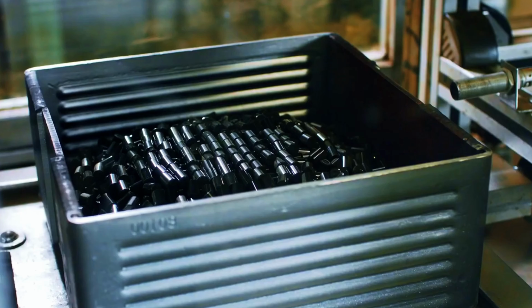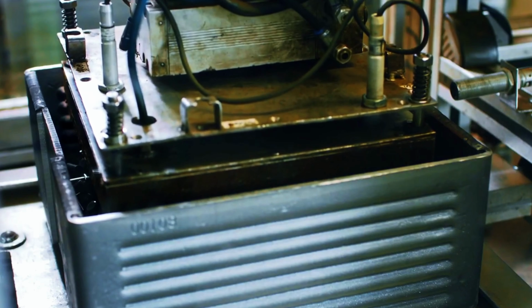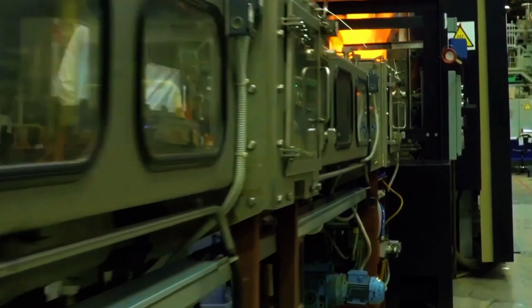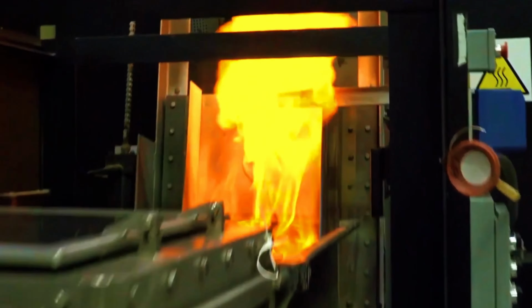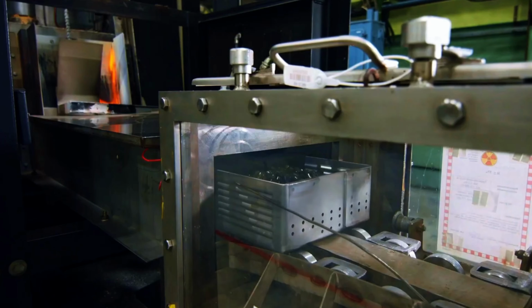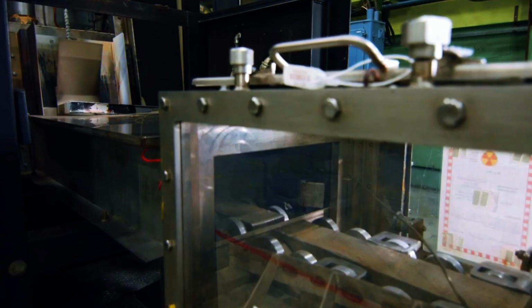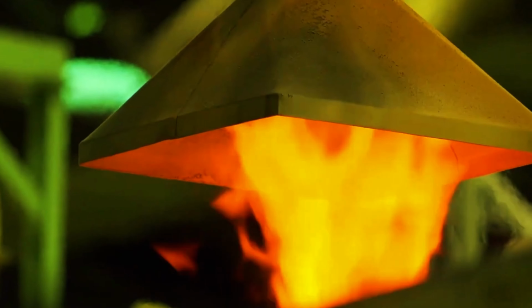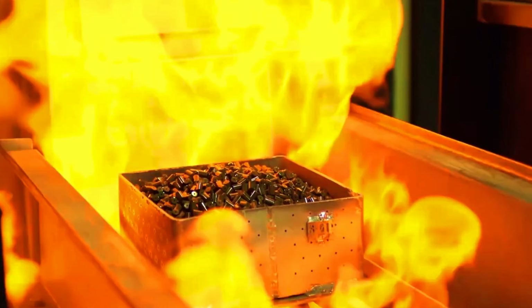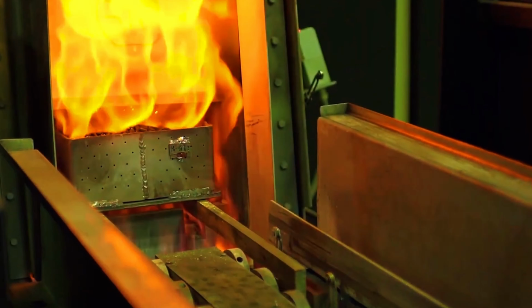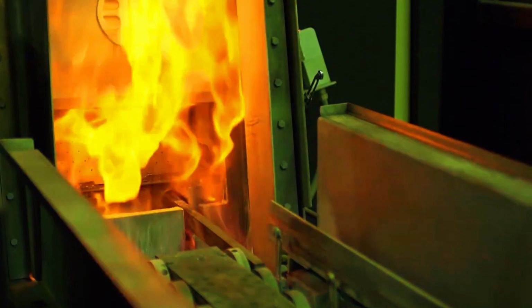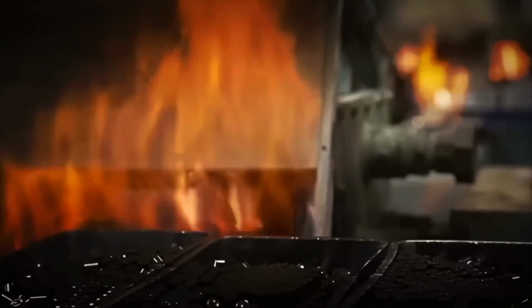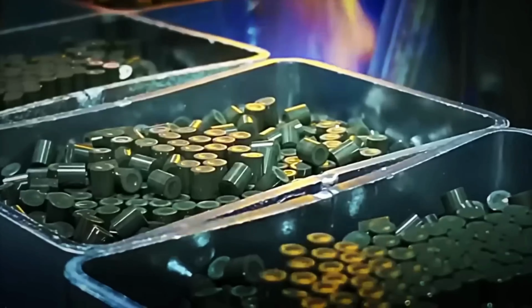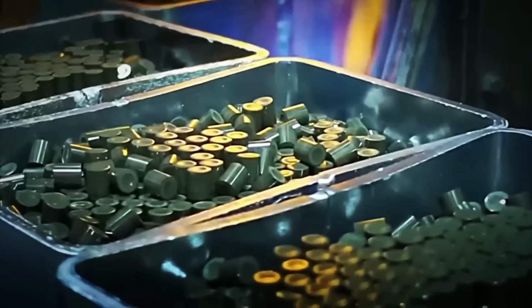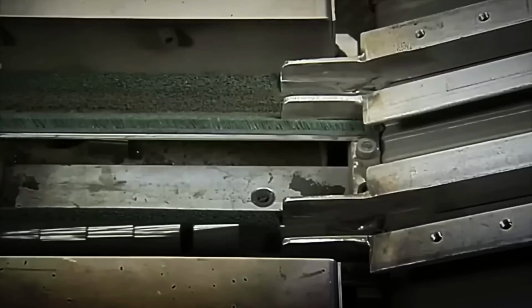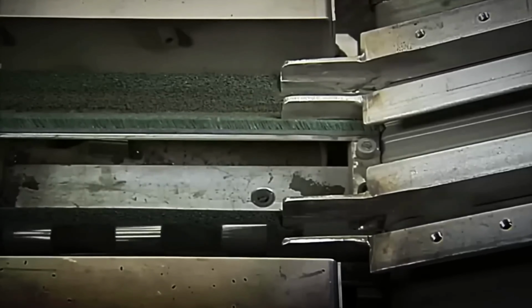Sintering is one of the most critical steps. Green pellets are loaded into high-temperature furnaces and heated to temperatures exceeding 1,700 degrees Celsius in a controlled atmosphere. During sintering, the powder particles bond together, increasing density and strength while reducing porosity. The pellets shrink and become hard, ceramic-like solids capable of withstanding extreme heat and radiation. Furnace conditions are carefully controlled to achieve the correct microstructure, because pellet density affects heat transfer and fission behavior inside the reactor. After sintering, the pellets are cooled and inspected.